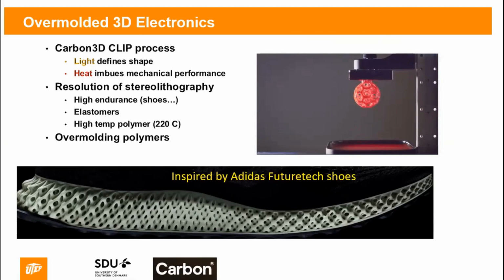The rest of the shoe is made traditionally. But what they are doing is using complex geometries to basically tune the coefficient of restitution so that when you put energy into the sole, it returns it. You could run faster possibly, and it's more comfortable. And what's really cool about this is I just told you the VAT photopolymerization has really bad material properties. It's relegated to photochemistry. Well, they've got it where they're making a shoe that you would step on 100,000 times through the life of the shoe. And these are very durable materials.